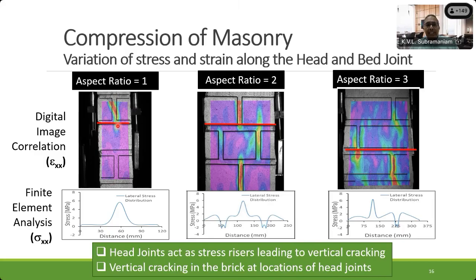And the tension in the mortar is what causes splitting of the brick directly below the head joint. Now, even when we went to higher and higher aspect ratios, anytime we had a head joint, we found that the tension was very, very high right here. So this is where the tension is very high, which led to cracking in the brick directly below the head joint. Same thing here. So wherever we are seeing head joints, we're finding that this tension that is produced in the mortar leads to splitting of the brick directly below the head joint. So these head joints act as stress risers and lead to vertical splitting of the bricks in the masonry.